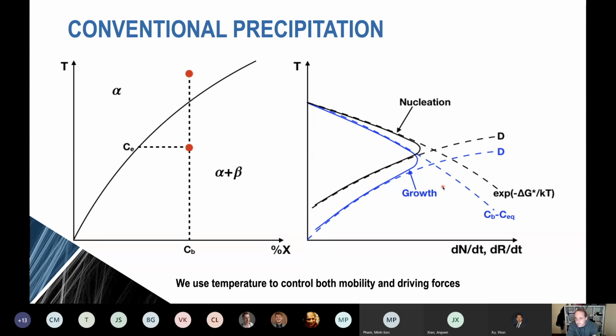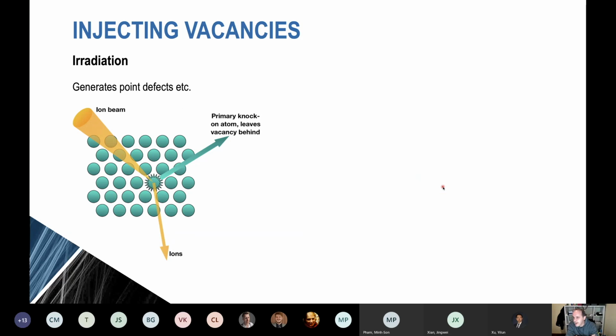And so certainly you can. And we know that there are different ways to create mobility in materials. In the sorts of materials that we're interested in, the mobility occurs by a vacancy exchange. And so any sort of process that we can use to inject vacancies into the material can give some mobility independent, or let's say partially independent, of the temperature effect. So irradiation is one way. And so certainly this is well known for people working in the nuclear industry. You can create point defects by irradiation, and those point defects can mediate mass transfer. And that's interesting, but it's perhaps not so easy to apply, and often we want to avoid this, in fact.